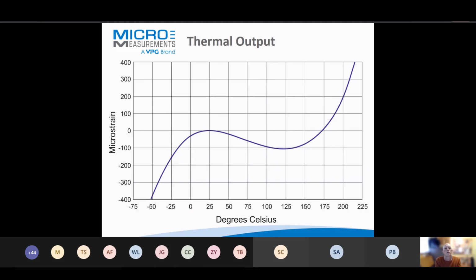Gauges are also sensitive to thermal effects. It sounds like a disadvantage, but actually this is an advantage in many measurement situations. This thermal output can be used to measure things like expansion coefficient. But if you take a gauge and bond it to the material for which it was intended, you will get this very strange S-shaped curve. The great thing about this is, around room temperature, it's virtually flat.